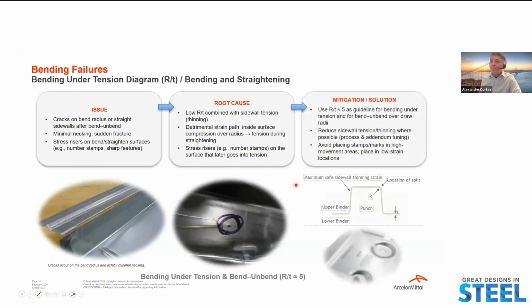As a mitigation, use a good correlation of R over T. We recommend 5 and above as a guideline for bending under tension, and reduce sidewall tension thinning where possible through process and addendum tuning, and avoid placing stamp marks in high movement areas.